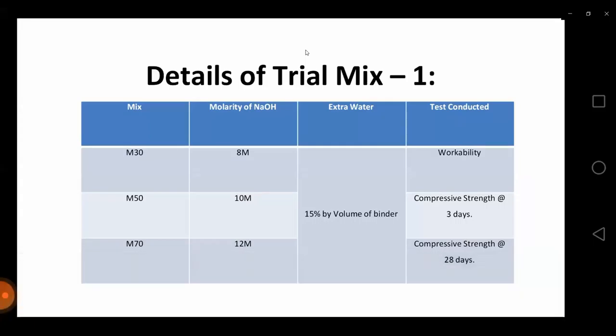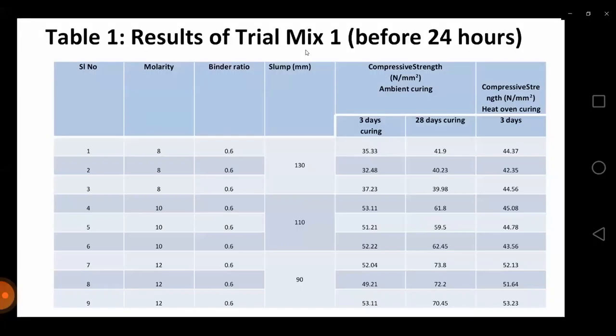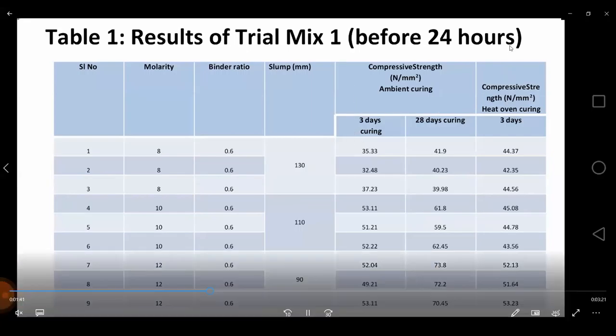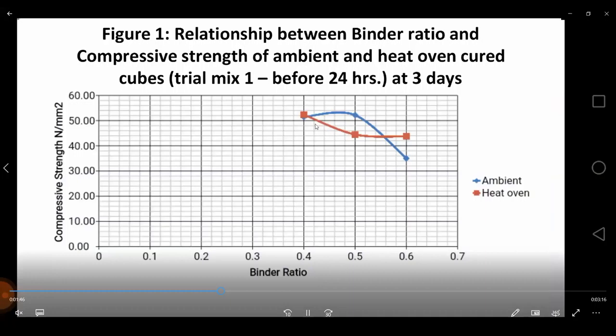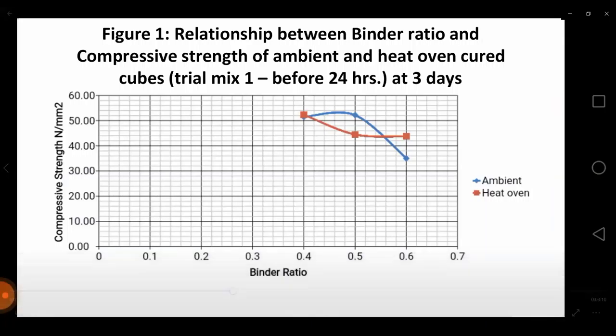This is the first trial mix details. In this, we have considered different molarity of NaOH, which is 8 molarity, 10 molarity, and 12 molarity. And table one shows the results of trial mix one, when we add the solution, sodium hydroxide and sodium silicate, 1 day before the casting of the specimens. And this figure one shows the relationship between the binder ratio and the compressive strength for both ambient and the oven cured cubes at 3 days.